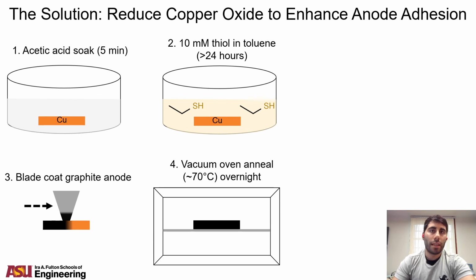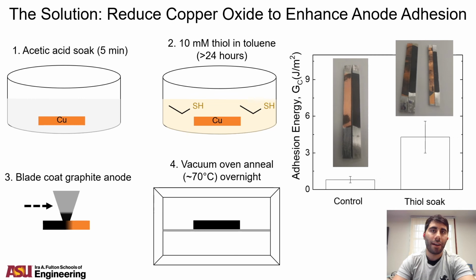It's well known that copper forms a very defective oxide layer, and this is what's thought to lead to the poor adhesion of the graphite anode. So we performed a very simple step where we reduced the oxide on the copper current collector while depositing a monolayer of a thiol, which prevents oxidation. And then we coated the graphite anode on top and observed significant increases in the fracture energy of the layer.